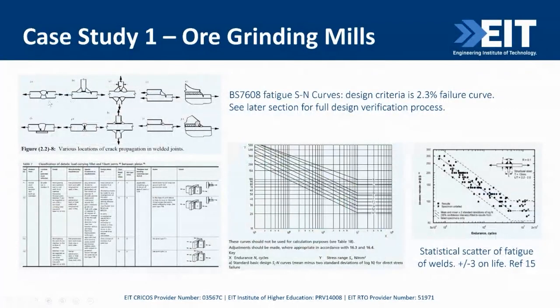So what you've got to do is go through every weld joint, whether it's a full pen butt, full pen T. You won't use fillet welds or lap welds in a mill like this. And look at all the potential fatigue cracking sites, the toe, the root, whatever. Determine what the classification to the 7608 code is. Determine what your fatigue characteristics is, and make sure you're below that. Always obviously using a 2.3% failure situation on your statistics. Your fatigue on laboratory weld specimens is plus or minus 3 on life. So you've got to use that mean minus 2 standard deviation, 2.3% failure, 97.7% success for your design criteria.